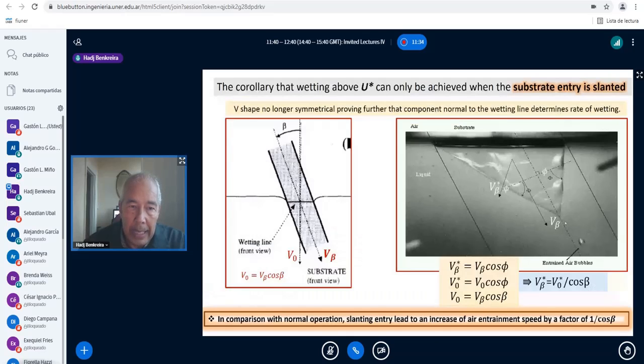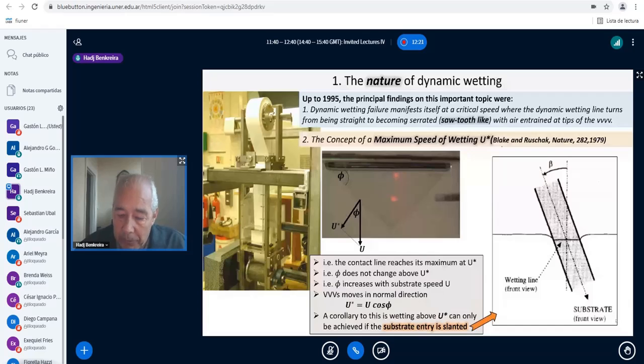So imagine in here, instead of going in this way, you enter the bath at an angle. So what will happen? The V's will be inclined now, as you see in this figure. And then if you resolve the velocities, you will see that effectively the speed of air entrainment will be increased by 1 over cos beta. So simply by slanting the web, you are going to increase the air entrainment speed. And this is a corollary of the concept of the maximum speed of wetting.